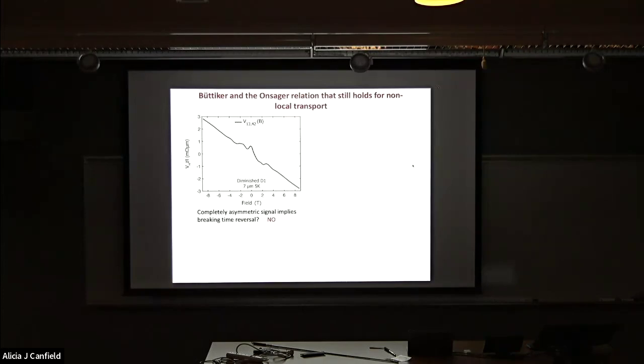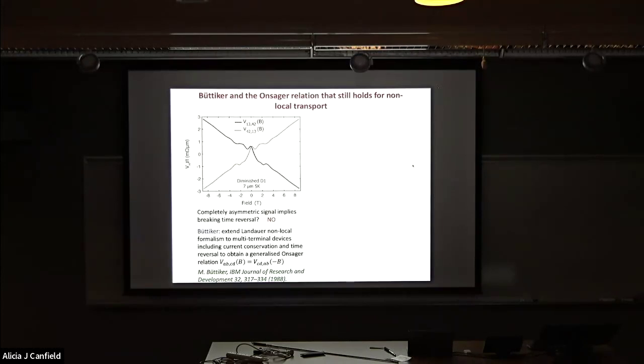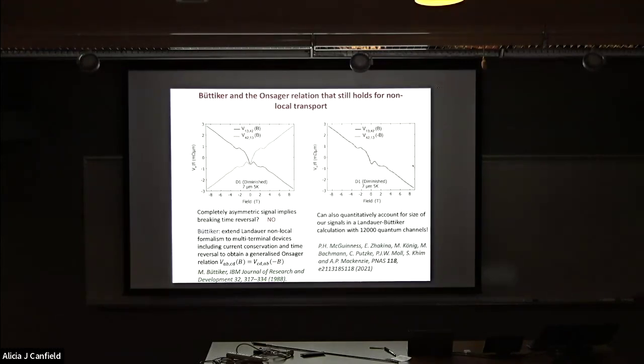It does not, because if you then go and read the famous work from Büttiker, who extended Landauer formalism to multi-terminal devices, including current conservation and time reversal, the generalized Onsager relation that you have to obey doesn't just involve reversing the field, it involves reversing the field and permuting the contacts. So they did that, that's what they measured. So you do the transformation and that's what you get. I mean, it's very super cute.